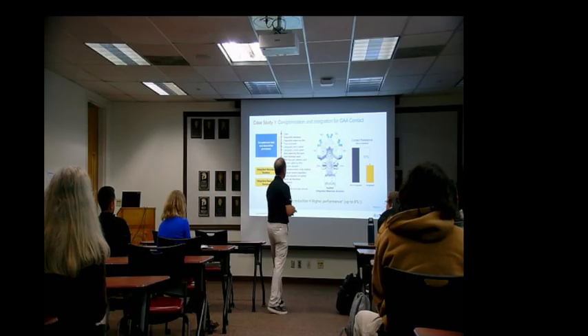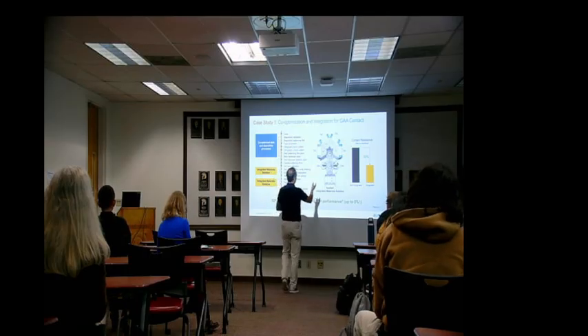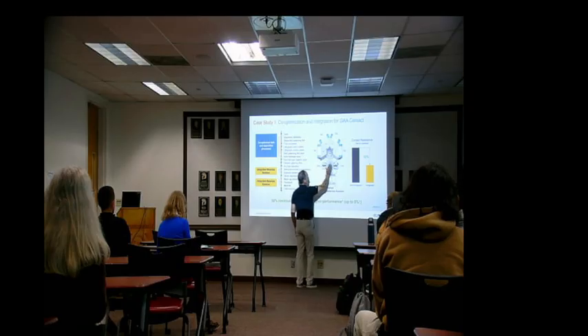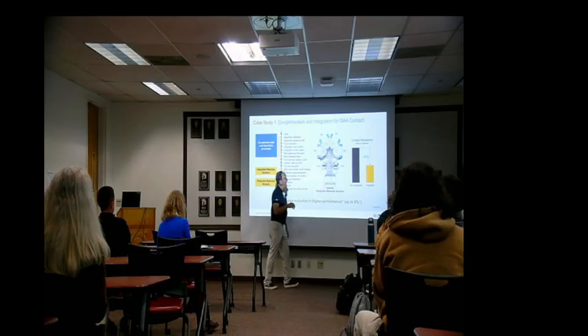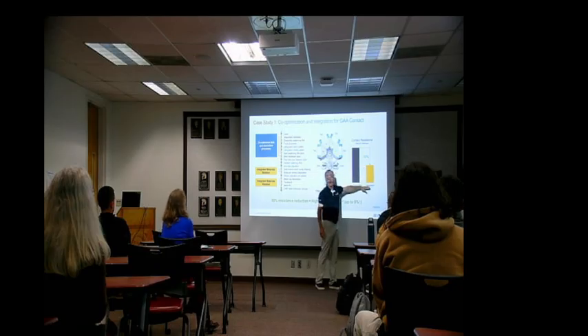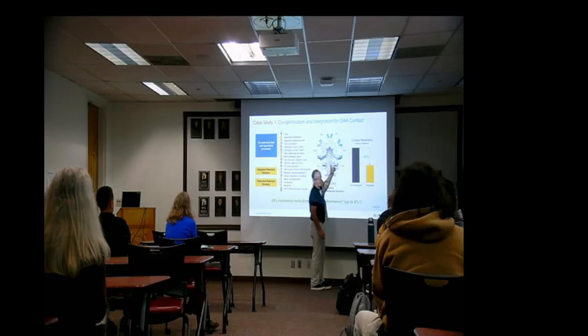So what we do is we start integrating these steps together on the same tool. Because this is very high vacuum, there's no impurity in here. There's no particles or impurity in here. Wafers go in, we pre-clean it, then we go run our epi. And when we do that, we get contact resistance that is significantly better. The tool's more expensive, but the contact resistance goes down.